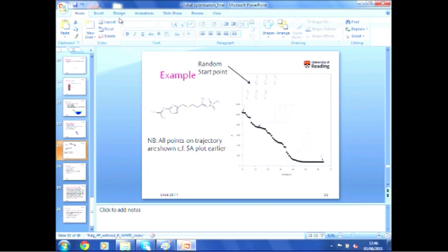I'll give you a very simplistic one, in the case of a structure which is, for example, an SO2NH2 group. The scattering power of the NH2 is roughly on a par with that of the two oxygens, so you can have three possible configurations, that, or that. The resolution of the data that we're using to solve is insufficient to tell us that, but we're chemists. So even I won't recognise in the output structure that the one it's settled on needs to be correct, but I'll look at the hydrogen bonding. If hydrogen bonding isn't satisfied, I'll flip it around; if it is, I'm a happy chappy. But at high resolution, it does pick up.